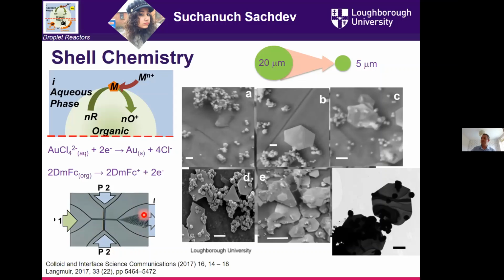And so we can tune the size of these droplets very easily by changing the flow rates or the ratios between these flow rates in the system. And we initially had thought about changing reactant ratios and adding other stabilizing or inhibiting molecules into the liquid to try and stop certain crystal planes growing. And before we even got anywhere like that, it turns out by just taking the same reaction but taking droplets of different sizes, you ended up getting spherical gold particles all the way up to platelets. And it was incredibly reproducible.